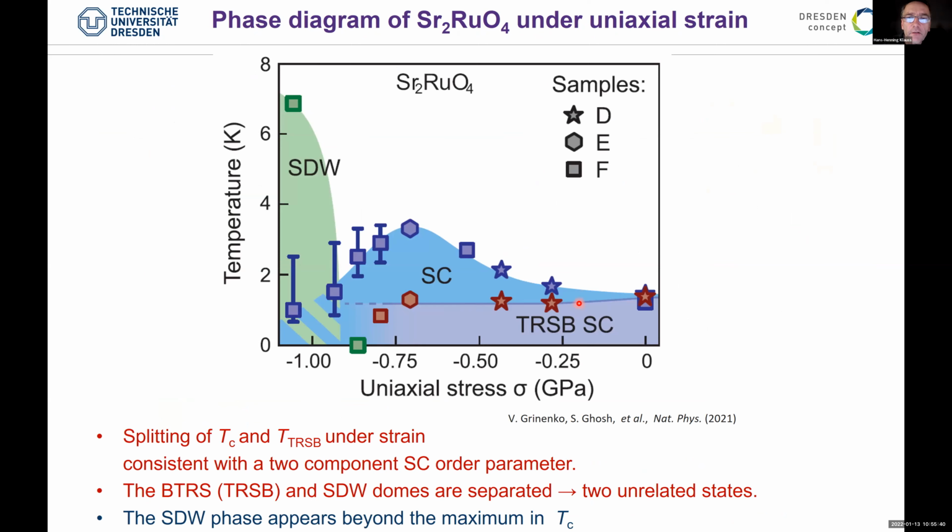Yeah, this is actually a surprise. In particular, it is basically temperature independent. If you start with weak uniaxial stress and then go beyond the Van Hove singularity, it goes down and somehow disappears. Unfortunately, these are long-time experiments, and we could not look closer at this region. But yeah, it is consistent.